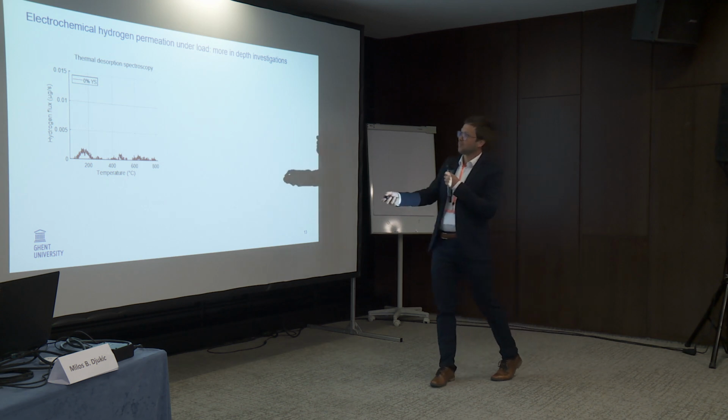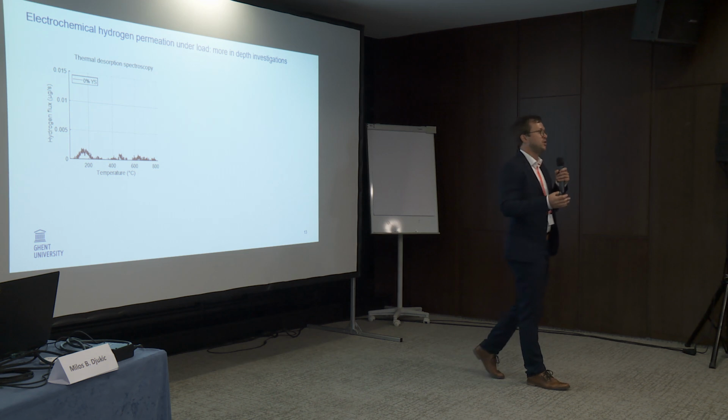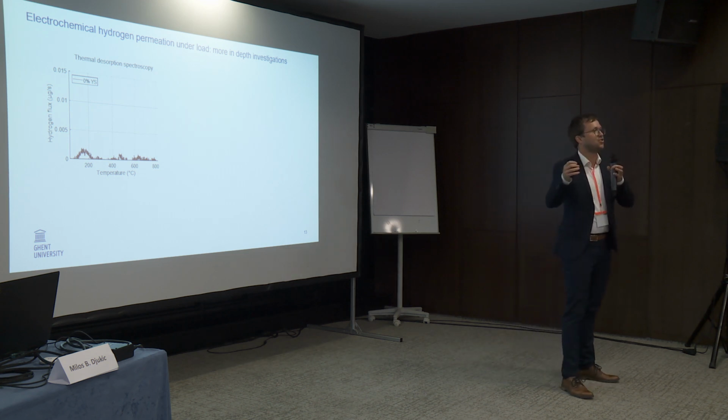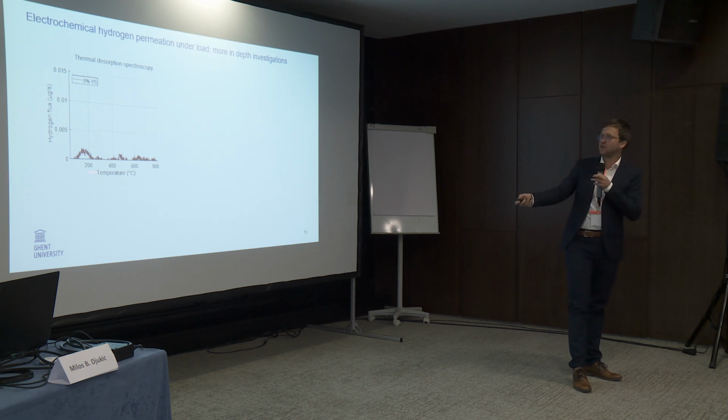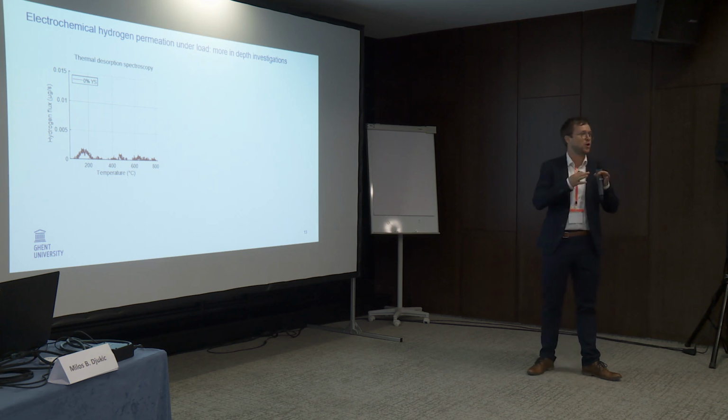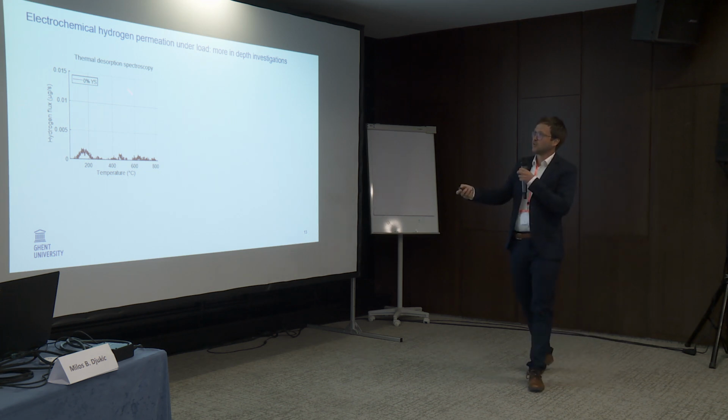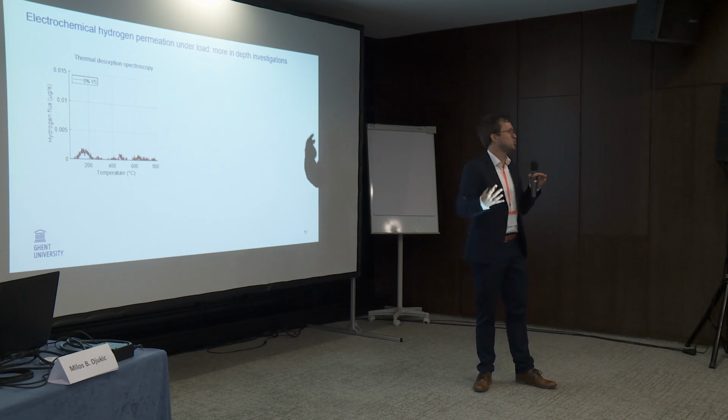And as you know, in the beginning we had no high temperature peak. Neglect this low temperature peak because there is quite some time in between the permeation testing and then the TDS testing, so you have effusion of hydrogen, so this first peak doesn't really tell anything, but the high temperature peak is very stable, so it will stay there. We also verified that by waiting different times. So 0%, no high temperature peak, the same as just with charging.